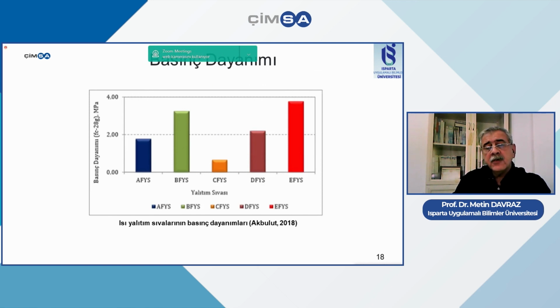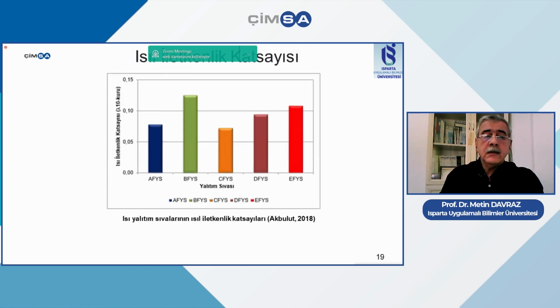For pressure resistance, you can see here as a function of the unit volume mass. And so for 28 gram, you can see here the results of the 5 samples again of the insulation plaster. So 3 of them are again above a certain level. For heat transference levels, coefficients, we can see here heat conduction coefficient, and you can see here again the results of the samples.